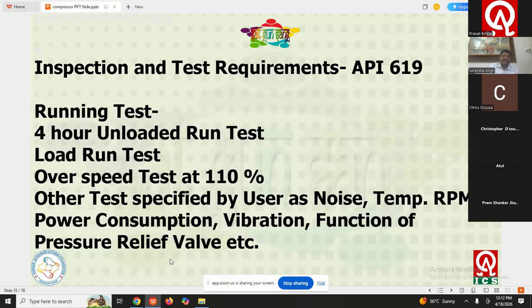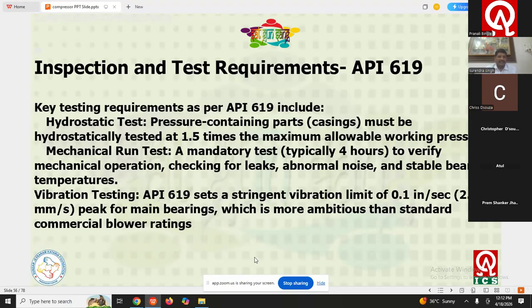Again, API 619 states that a 4-hour unload run test shall be there. Overspeed test at 110%, 11% times to be conducted. Again, the same tests are there: noise, temperature, RPM, power consumption, vibration, function of pressure relief valve. All are the common tests which we have discussed in API 618. For the 619 hydrostatic pressure test, the same requirements are there. So 1.5 times the allowable working pressure has to be tested. Mechanical test has to be done for 4 hours, and the same check parameters are there.